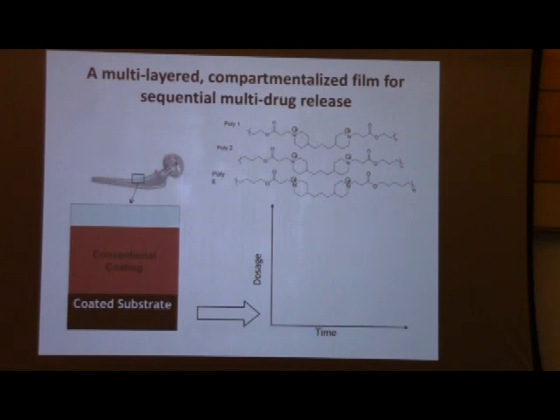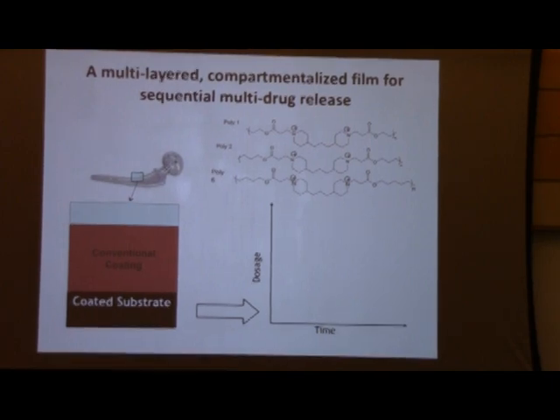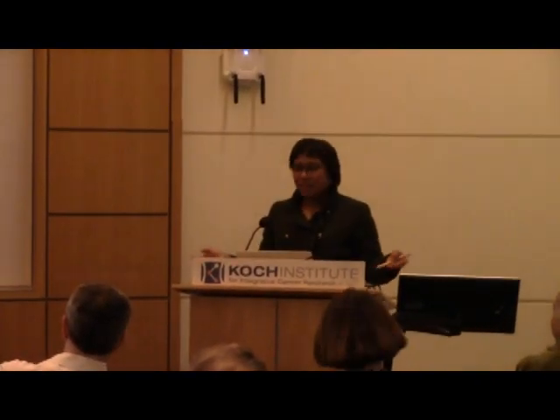The idea is that you can take a conventional coating that might be a polyester like polylactic glycolic acid. It will degrade in a very controlled fashion. But because it is a polymer and you're trying to create a blend with, let's say, a protein-based drug, it turns out that it's going to phase separate at very low concentrations of the protein. And the reason for this is that when you have a large molecule like a polymer, and you blend it with something else, that gain in entropy, going way back to thermodynamics, you remember that when you mix two things together, they want to mix because you increase entropy. But when you have a polymer chain, you already have these units linked together to create a very large molecule. So when it blends with something, you don't get as much entropy. So they don't want to mix as much as most materials do.